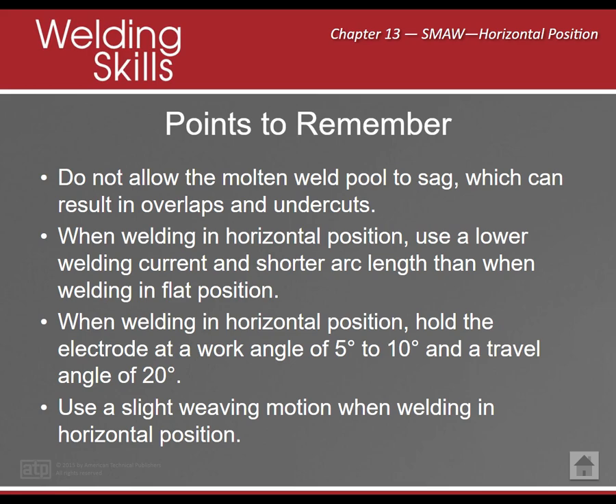Okay. Also, when welding in the horizontal position, you can use a lower welding current and a shorter arc length. So if you're in the flat position on a 1/4 of an inch piece of material, let's say you're at 120 or 125 amps, okay, with an 1/8 of an inch arc length. You move to the horizontal position, you're going to have maybe 110 or 115 amps, and you're going to be about a 1/16 of an inch arc length rather than the 1/8 of an inch arc length.